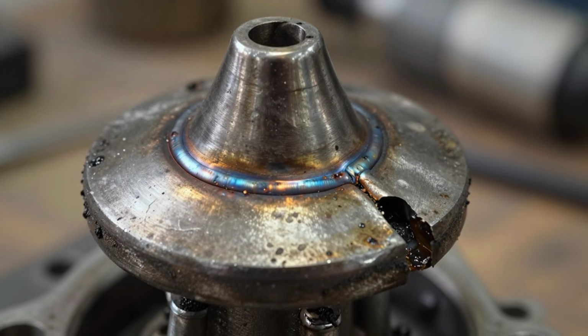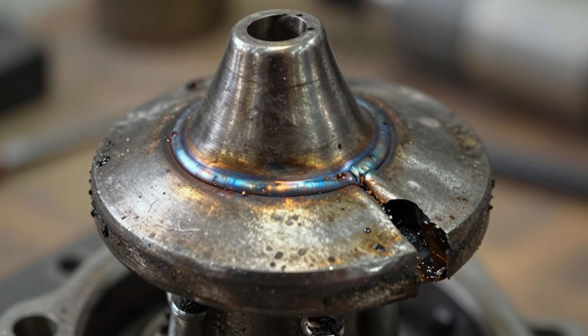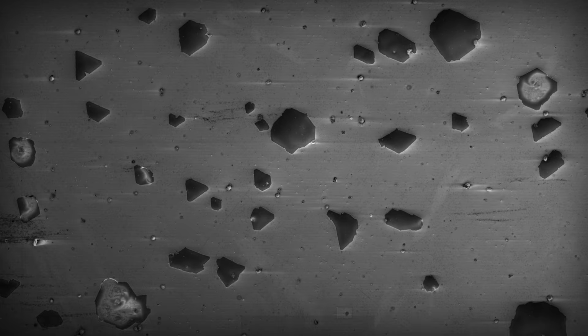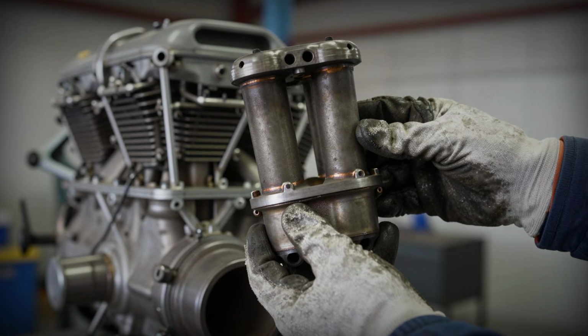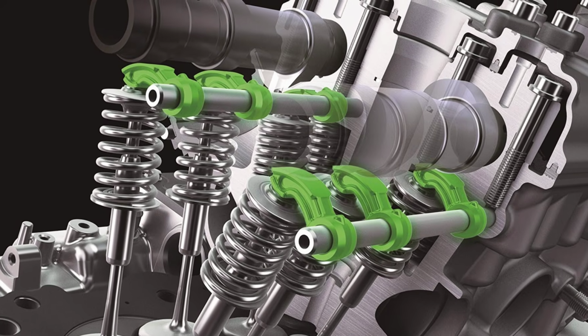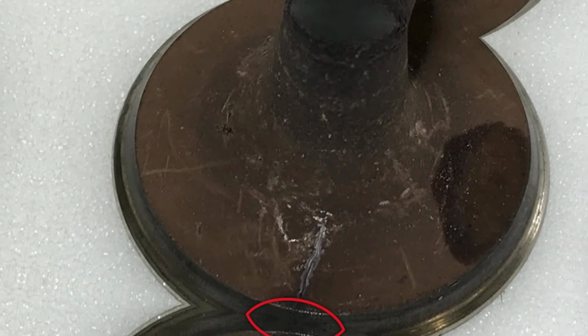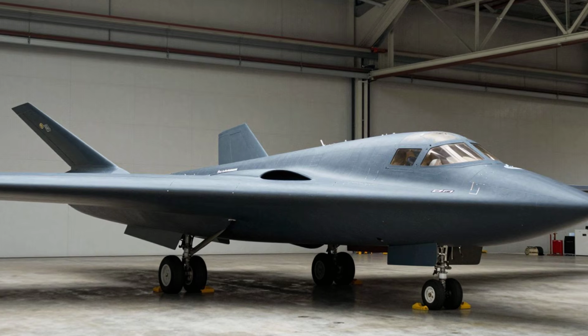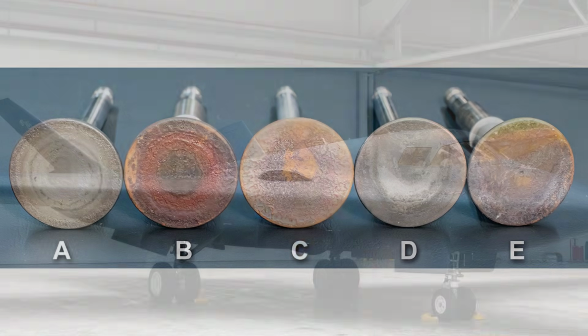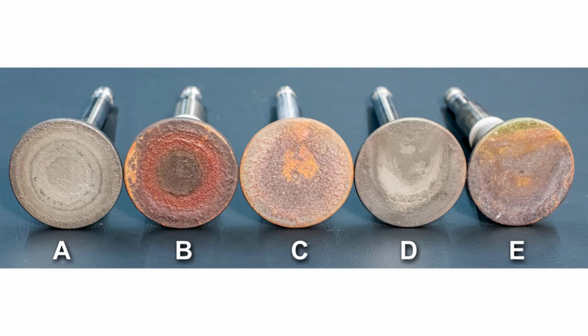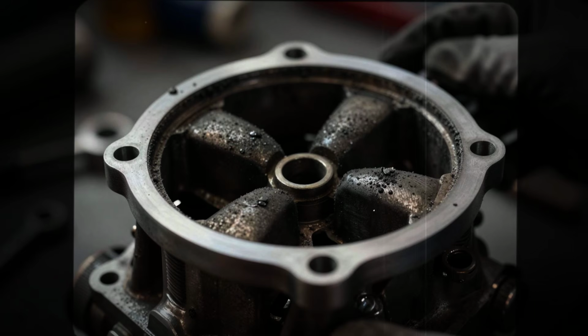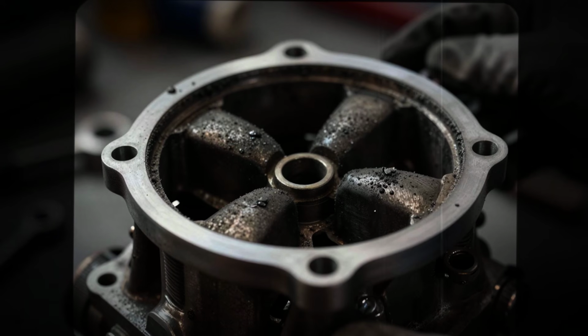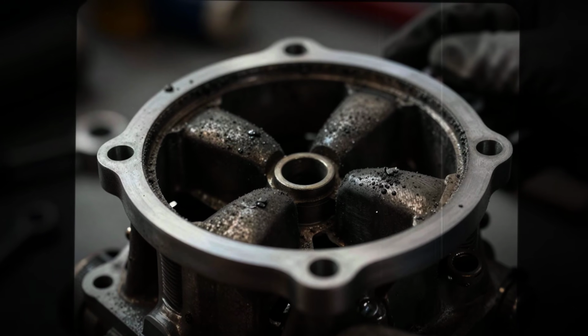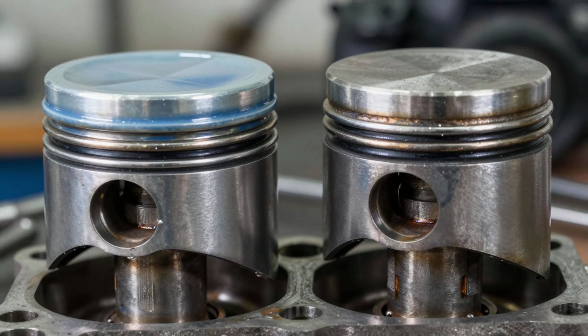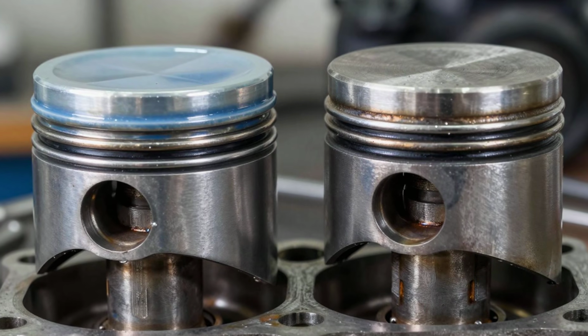Without a lubricant, those peaks do not just slide, they fuse. For a split second, steel and iron weld together at the atomic level. Then, as the valve lifts, those bonds rip apart, tearing out microscopic chunks. What is left behind are pits, scars, and the slow spiral toward catastrophic outcome. In the old world, lead's oxide layer acted as a sacrificial film. It sheared before the steel ever could, keeping friction low and stopping those micro-welds in their tracks.